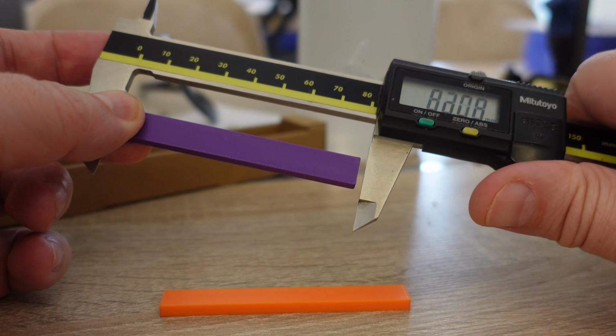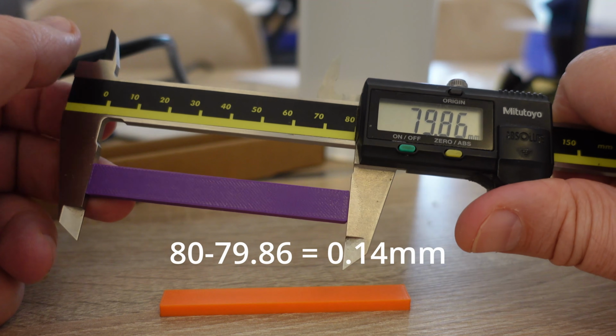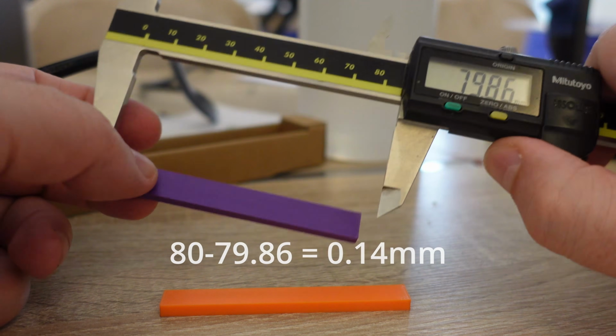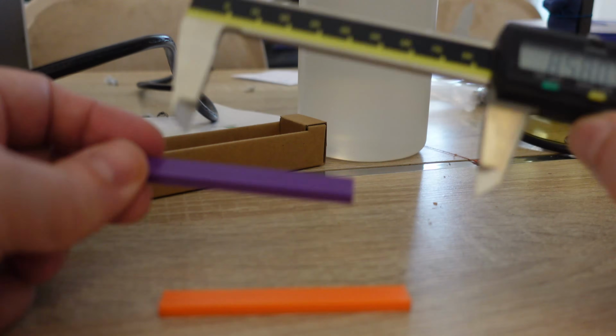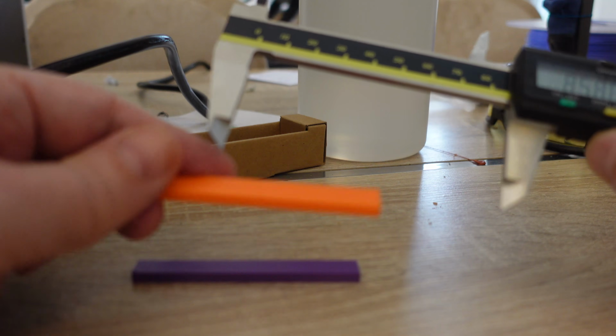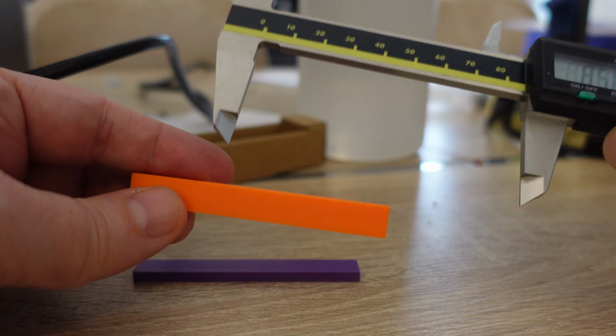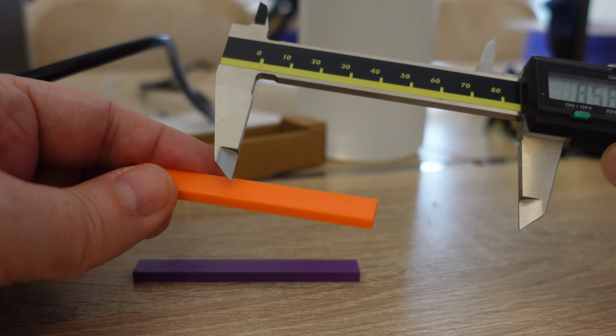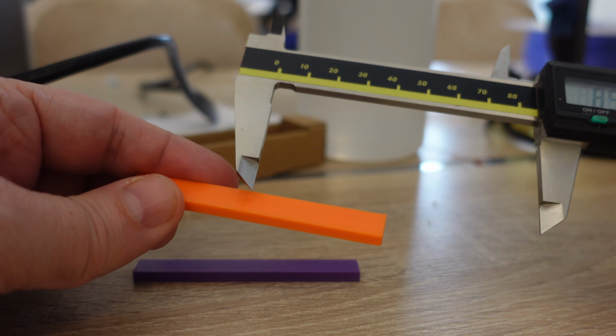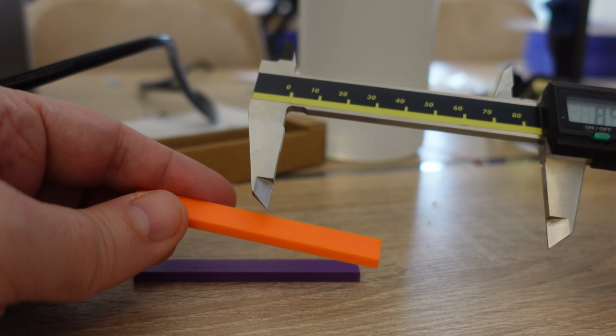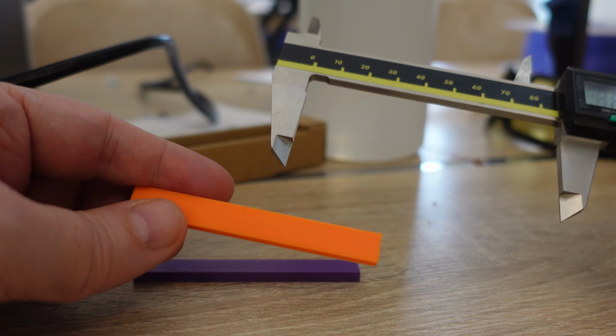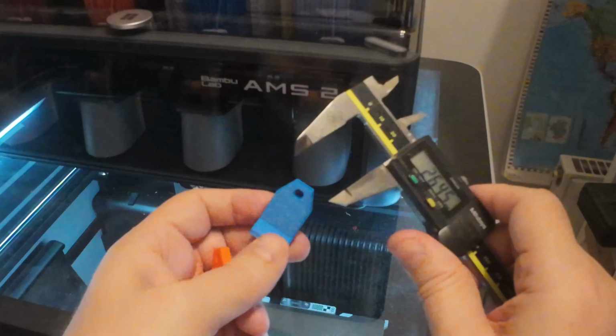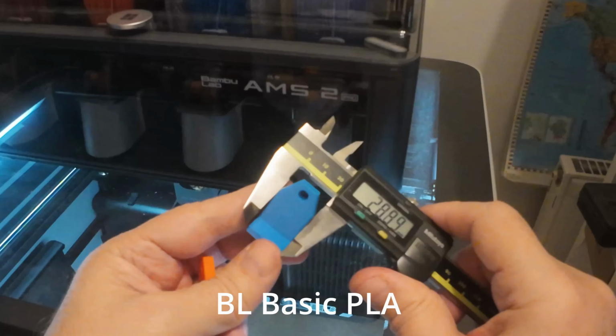And this is PETG. 0.14 millimeters. This is a little bit bigger, but acceptable for the PETG. Only for the PLA, usually I can measure a smaller shrinking. And probably this is the reason why it has a weaker bed adhesion without glue. It shrinks minimally, especially with this additional cooling, and then it shrinks and removes. I noticed on the smaller test object the difference is not big.